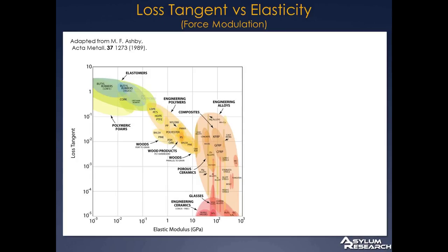Since we're talking about material properties, I thought it would be useful to look at the range of material properties, the loss tangent and the elastic modulus. I took this figure from a paper by Ashby in 1989, adapted a little bit and colored up a little bit. It's a really nice little paper. I recommend it. What he did is he plotted the elastic modulus of materials, ranging from 10 to the minus 3 to 10 to the 3 gigapascal along the x-axis. This does not include a lot of very soft biomaterials, for example, which can be down in the kilopascal range, so this only goes down to megapascal or so.